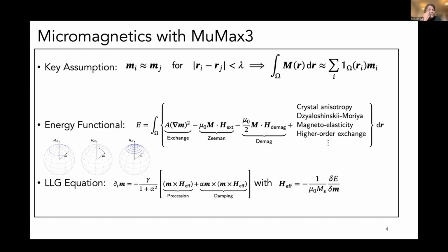And what is the typical cell size you choose for these simulations? Normally the cell size is around maybe 2 nanometers, and we generally have a lattice of like 300 by 300 cells. It should be less than the coherence length. Yes. In XYZ, you take 2 nanometers each, right? Yes, that's correct.